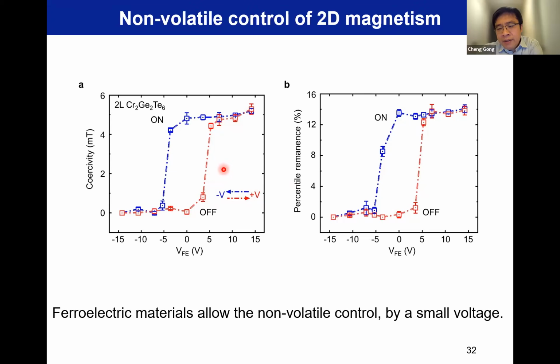Later on, we also redesigned the experiment by removing the silicon oxide substrate. So we directly used also around 5 volts to flip the ferroelectric polarization and the magnetic property, and we observed the same non-volatile control. So this is certainly a multiferroic effect based on ferroelectric polarization-dependent magnetic properties. But for that vision, half-metallicity is still on the way. As I said, there are really a lot of challenges, but you can see such ferroelectric control of 2D magnets could enable many things.